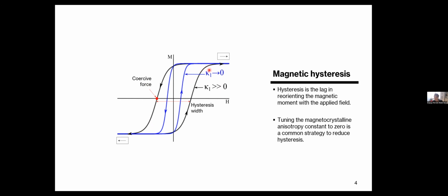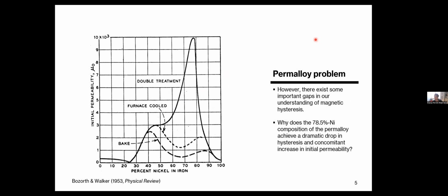So when we're developing these soft magnets in the community today, the common strategy is to tune the alloy composition so you can tailor this anisotropy constant to be as close to 0 as possible, because the larger it is, the more it generates hard magnets, which have other applications. But this has actually led to certain outliers, and I'll start with a classic example, which is the Permalloy problem.